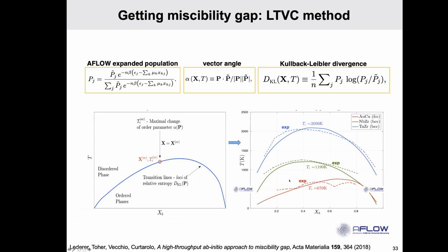But the bottom line is you get a temperature that is related to the temperature of the real miscibility gap. It works quite well, and it is found easily in a matter of hours, well, maybe days of calculations. Something that, from an experimental point of view, might be inaccessible, because to look for the miscibility gap, you need to make a mixture, you need the mixture to be a solid solution, and then reduce the temperature and wait. Remember, lower temperature, lower kinetics, and wait forever and ever until you have dissociation, okay?